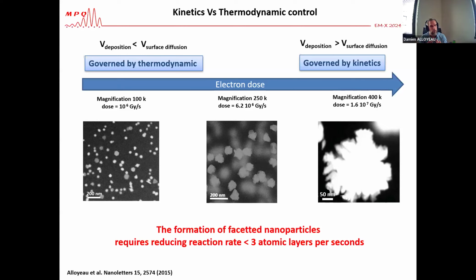The ability of the crystal to reconstruct well-faceted morphologies. So when the growth speed is low, you are governed by thermodynamics, meaning that you give enough time to the system to reconstruct faceted morphology. When you increase the growth speed, you are governed by kinetics, and the surface diffusion is not fast enough to reconstruct your thermodynamically stable facets. And with this type of imaging, we have been able to determine that the formation of faceted nanoparticles, for the case of gold, requires reducing the reaction rate below 3 atomic layers per second. So this was great. This was work we have done a long time ago.